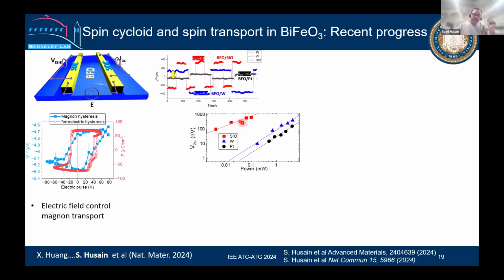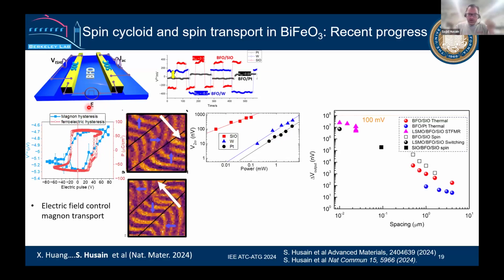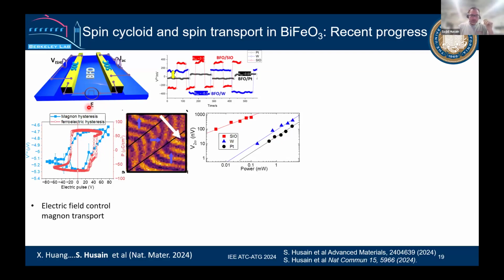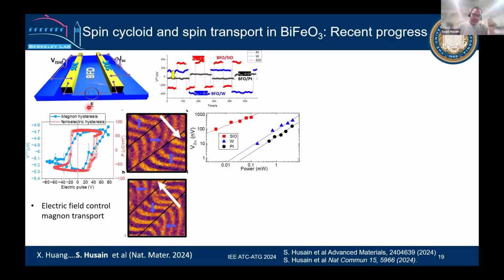And then the electric field scan: the red is the polarization hysteresis in the material. And then blue is the output voltage as a function of electric field, which basically overlaps with it. It means that we can control the magnetization or antiferromagnetism using an electric field. And this is some imaging. If you look closely, these stripes going this way change to this way when we change the electric field direction. It means that your antiferromagnetic cycloid domains are changing as a function of electric field. And of course, the output is real and increasing with the spin orbit coupling material.